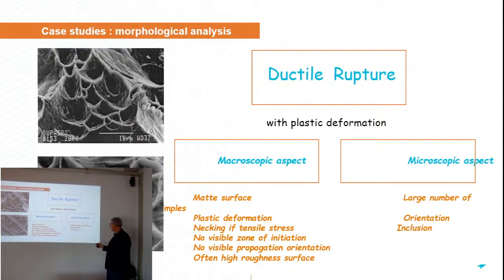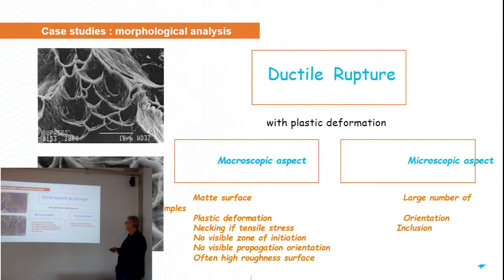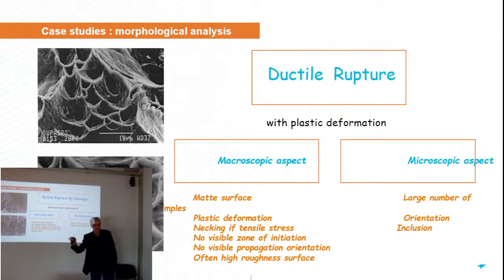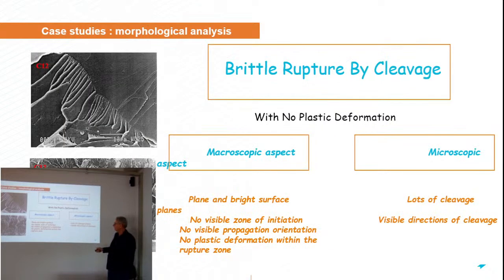And when you go to the microscopic scale, you can see a large number of dimples, orientation, and inclusions. These are brittle, non-deformable phases, around which the plastic deformation can occur. The brittle rupture by cleavage is given here, where the fracture surface crosses the metallurgical grain of the material.